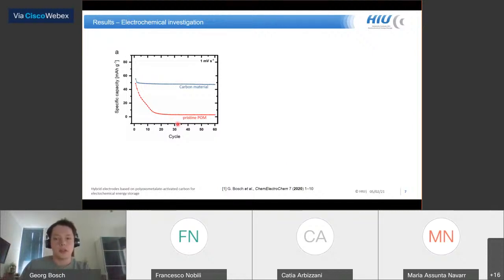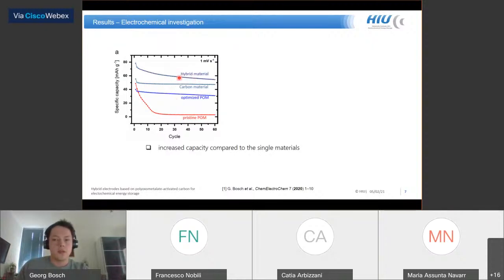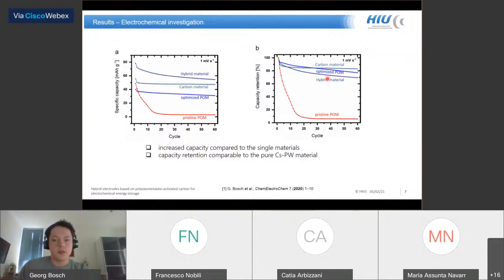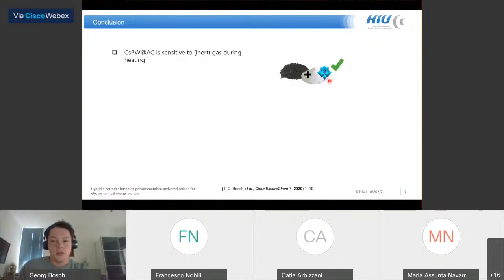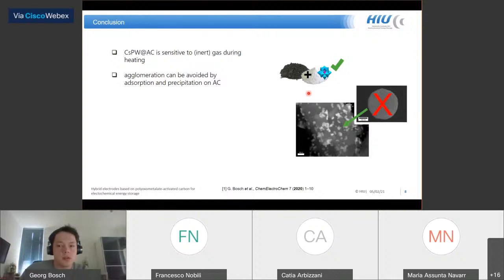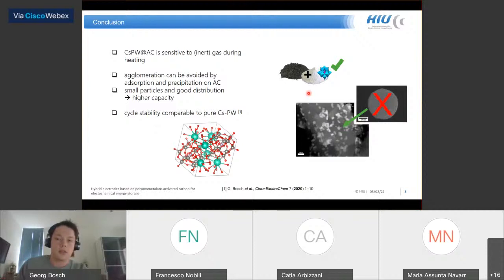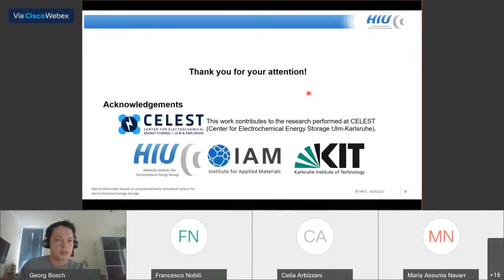Compared to the untreated polyoxometalate, the cycling stability could be increased, as known from literature, by heat treatment. And the combination of polyoxometalate and activated carbon in a hybrid material leads to a further increase in capacity, and the capacity retention is comparable to the pure polyoxometalate material. It can be concluded that the hybrid material is sensitive to inert gases during heating. The particles could be distributed well on the activated carbon, and agglomeration could be avoided. The small particles and the high distribution lead to an increase in the capacity, and the cycling stability is comparable to the pure polyoxometalates. Thank you for your attention, and these are my acknowledgements.